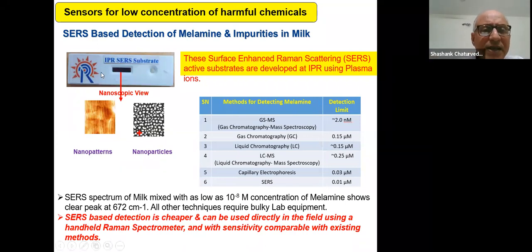What we found is, using plasmas, we can produce nano patterns or nanoparticle arrays on different sensors. We can make it even on paper or on some other materials. These sensors, these substrates, right now the cost is something like 50 rupees each to us. You then use a handheld Raman spectrometer, which comes for around 12 lakhs or so. So in the field, you could test samples and detect chemicals as low as 10 nanomolar concentrations. That is what we are able to do. So it's basically a question of being able to detect very low concentrations of harmful chemicals in the field. It could offer an option there.